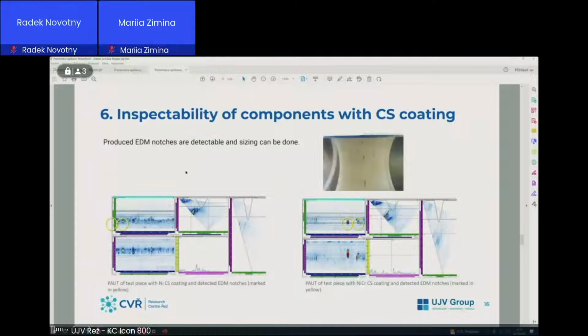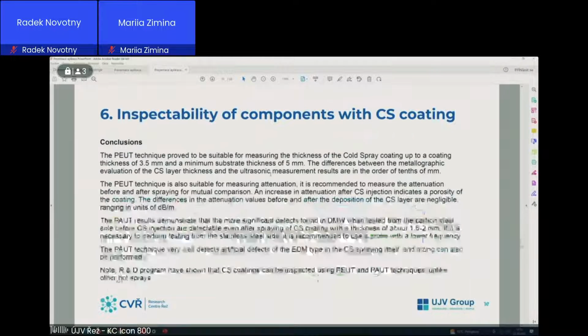Here is an example of detectability and sizing of EDM notches. And again, it works like with samples of steel material. So, conclusions, there is not so much time. The main conclusion is that cold spray coatings can be inspected using pulse echo, ultrasonic testing, and phase array techniques, unlike other hot sprays.